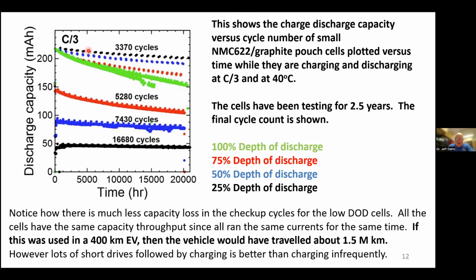These data points up near the top represent every 500 hours, for all of the cells, we did a 100% state of charge range. So we call this a checkup cycle. We're cycling along at 25% depth of discharge, but every 500 hours we do a checkup cycle to see what the capacity would be if we did a 100% state of charge cycle.